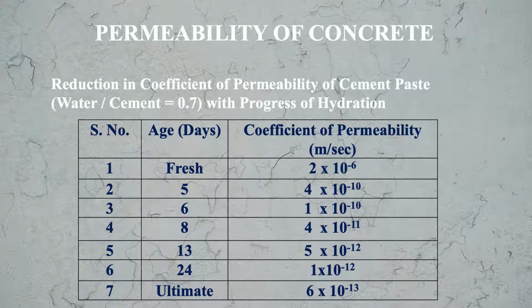If we look at 5 days, then it becomes 4 into 10 to the power minus 10, means it is reducing. If you look at 8 days, then it is 4 into 10 to the power minus 11, again reducing, going down. If you look at 24 days, it is 1 into 10 to the power minus 12, going down. And finally, permeability coefficient is 6 into 10 to the power minus 13. So as you see, with age, the coefficient of permeability is decreasing.